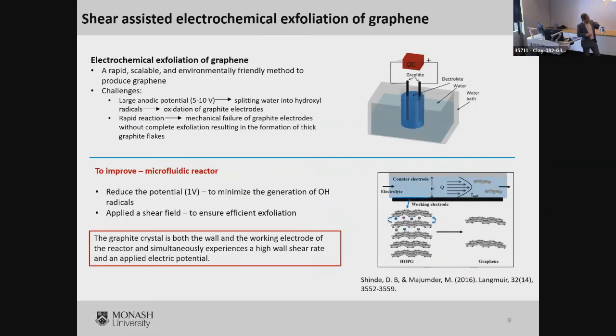One of the methods to make graphene from graphite is electrochemical exfoliation. It turns out that one of the companies in Western Australia, First Graphene, actually manufactures graphene by electrochemical exfoliation, which typically uses anodic potentials, and you exfoliate the graphite into small flakes. But the reaction is usually rapid and you need a large potential, 5 to 10 volts. What it ends up is essentially you split water and then you have oxidized graphene species, all right? And also when they are doing this method, it turns out that the graphite electrodes mechanically break and you end up with a product which has got thick graphite particles as well as graphene.